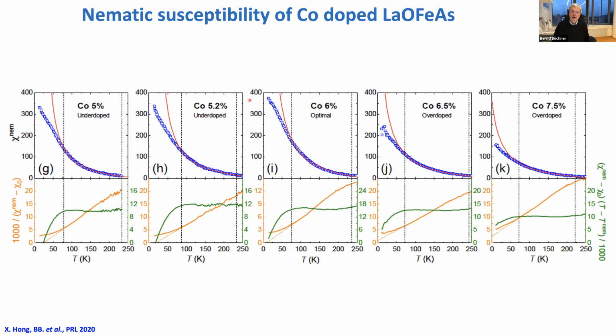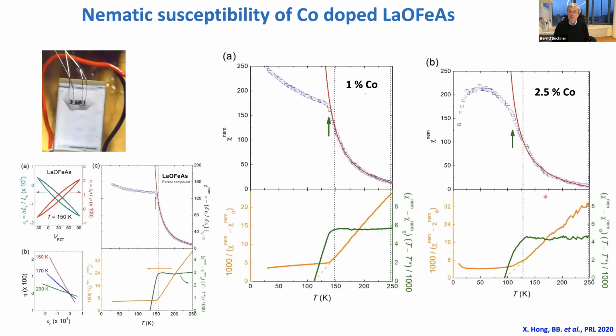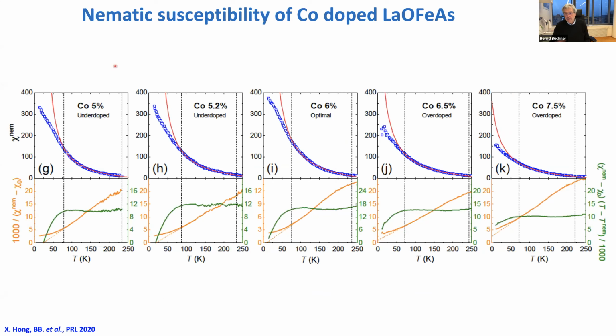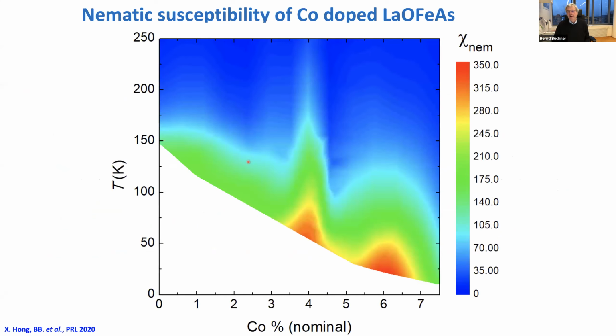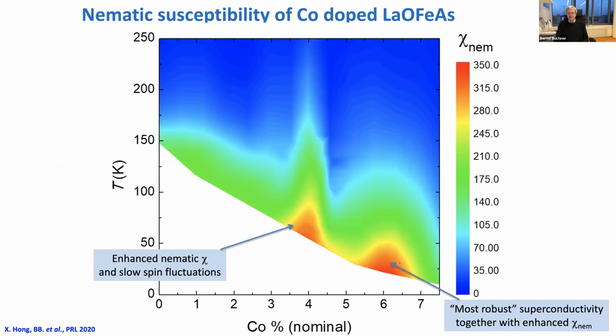And if you go to underdoping, it also becomes much smaller. It also becomes smaller when you go to the parent compounds or to these strongly overdoped compounds. So without any manipulation of data, you just take the raw data and plot that as a function of doping, and you end up with this diagram. And then you see what I would call a double dome feature for this nematic susceptibility. And of course, this is mimicking our superconducting dome.